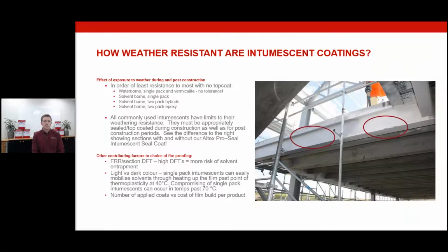All your commonly used intumescents have their limits to their weathering resistance. We're talking single pack here. They must have an appropriate sealer or a top coat applied during the construction, as well as for post-construction periods. You'll see in the photo on the right, we've had one of our products specified for use onto our single pack solvent-borne intumescent. The grey on the left-hand side has been coated with our Altex Pro Seal intumescent seal coat, which is designed to keep water out, but also allow solvents out of the actual intumescent coating to keep on curing.